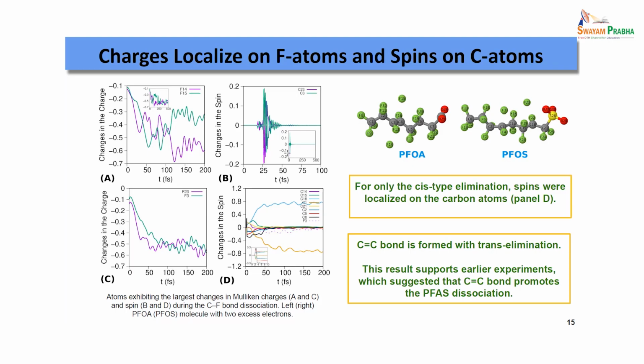Essentially, we found that for only cis type elimination, spins were localized on the carbon atoms. You can see here, these are the spins which are opposite. So as a whole, the system is always non-magnetic. One case it is anti-ferromagnetic, another one is non-magnetic. Have you heard of these words, anti-ferromagnetic and non-magnetic? So here one spin is up, another spin is down, but exactly their magnitudes are the same. So this cis type case is exactly anti-ferromagnetic type. Whereas in the trans elimination, we find the system to be completely non-magnetic. There is no spin.